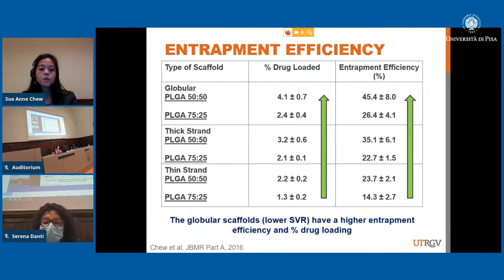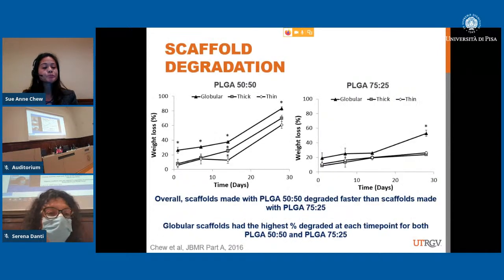So then the other thing we wanted to do as we characterized was to check the percent drug loaded and entrapment efficiency. And again, this is also based on the SVR, right? When you have a scaffold like the globular, where you have low SVR, we were able to have a higher entrapment efficiency and higher percent drug loading because there was less surface for the drug to get lost during the fabrication process, right?